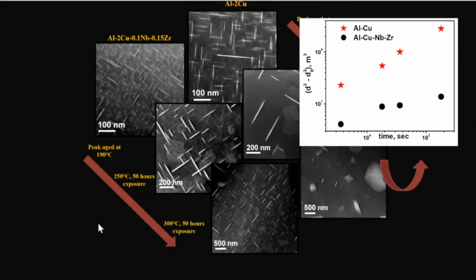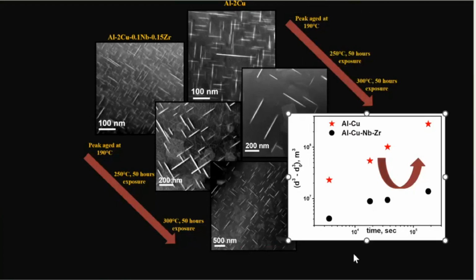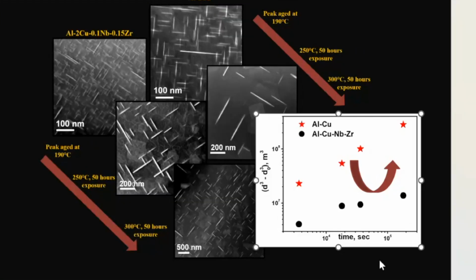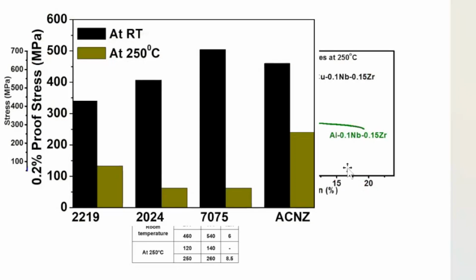On the left-hand side, you can see that our alloy, aluminum 2 copper plus niobium zirconium, inherits a very fine distribution. Even at 250 degrees centigrade, 50 hours, they do not coarsen. At 300 degrees centigrade, it coarsens. You can see the scale, but not as large as the comparable aluminum copper precipitate, which is given there. Simulations, these are phase field simulations, show that aluminum copper coarsens very fast, but the aluminum copper niobium zirconium is very sluggish. It doesn't coarsen. Therefore, it retains strength. And this is the comparison.